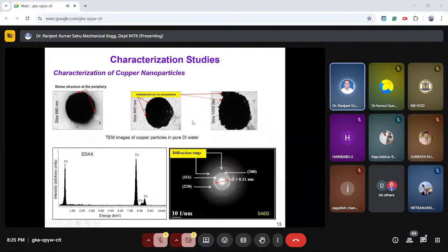Also, by visual inspection, 4 hours after the collection of this colloidal debris, it was observed that the dispersion stability of the copper particles in pure DI water was poor. That means we can say the sedimentation or settling of copper particles in the DI water takes place very quickly.